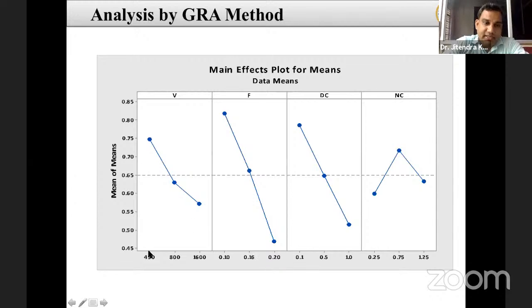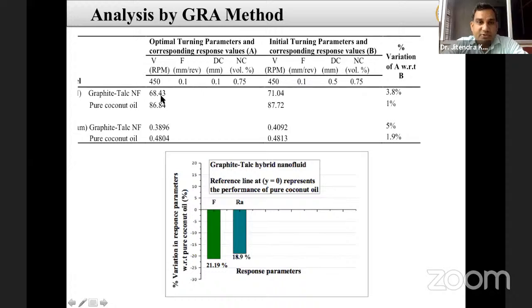So we see that 450 is a better one, with feed 0.1, depth of cut 0.1 and 0.75 nanoparticle concentration. It is good for further application. So we optimize those parameters: 450, 0.1, 0.1, 0.75 concentration, we calculate the cutting forces, and this is the term for the surface roughness. So the cutting forces for nano cutting fluid and pure coconut oil, we obtain this optimized data.